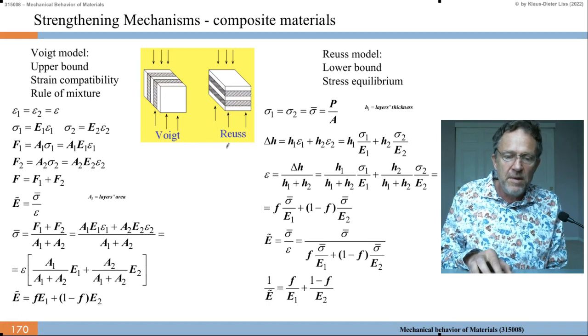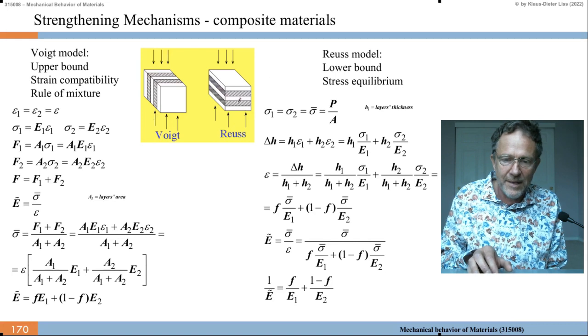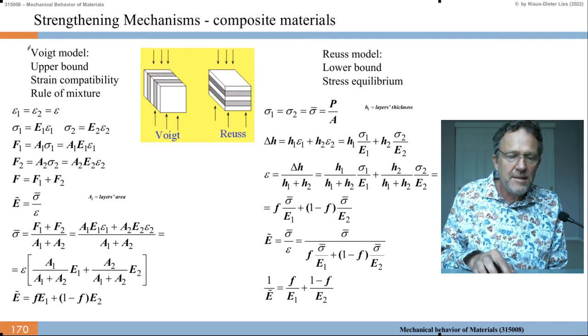Either we apply a compression or tensile stress perpendicular to the stacking, so along the normal of the stacking, or here parallel to the stacking, so in plane to the stacking or perpendicular to the plane of the stacking. That leads to the Voigt model and the Reuss model.